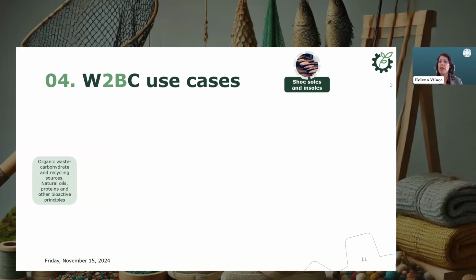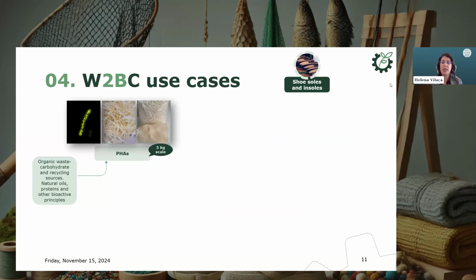Going for the footwear, we started with different organic waste carbohydrate and recycling sources, and also different natural oils, proteins, and other bioactive principles. And with this, we have produced different PHAs, as I said, with a wide range of properties, namely a quite wide range of crystallinities. They are produced both by biogenesis and by chemical routes. Of course, the chemical routes are the chemical modification of the PHAs produced by biogenesis. In this case, for biogenesis, we have been using cyanobacteria. As for the PHAs modified through chemical approaches, we have been able to go to a 5 kilogram scale per batch and using solvent-free methods.